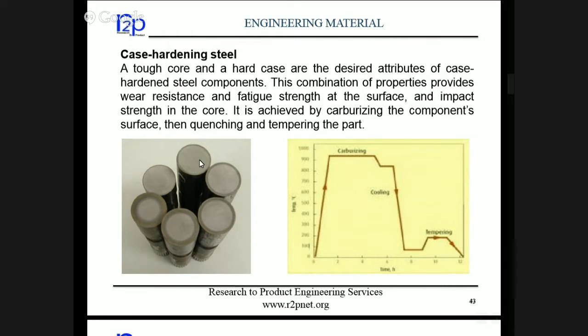And the most popular process for case hardening is carburizing. In carburizing, the temperature which we heat it to, we take it to the austenitic range, where we can add carbon into the low carbon steel. So generally the carburizing steel is low carbon steel, maybe 0.2% or less than that. So we have to build carbon into that.